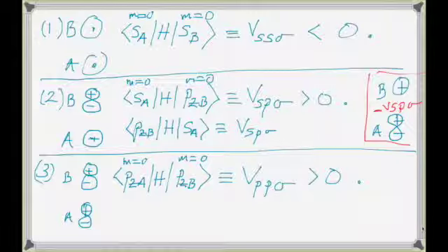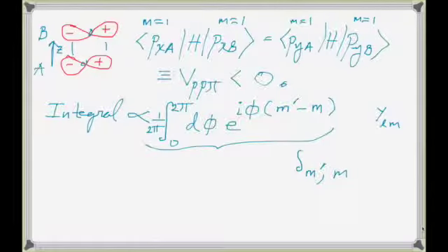Okay, so all the matrix elements we're going to be writing down when we do silicon are in terms of these things that we've just defined here. That's it. And these are a magnitude, and that magnitude is determined empirically to give you the best fit to the actual band structure, as I said, like band gaps and effective masses. And we then are going to be dealing with the angular dependence and the k dependence when we construct this Hamiltonian as a function of k.